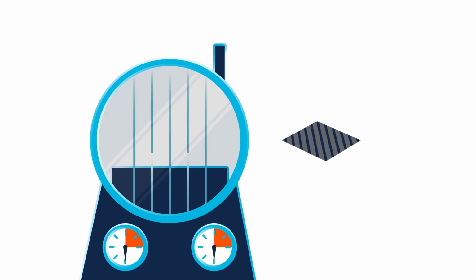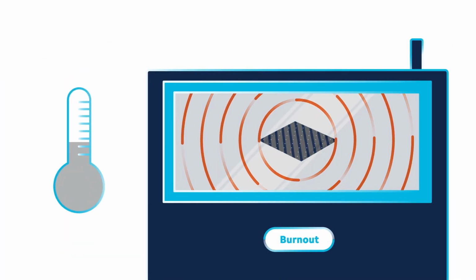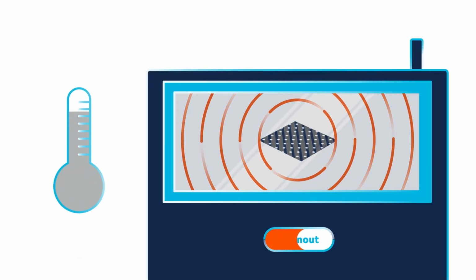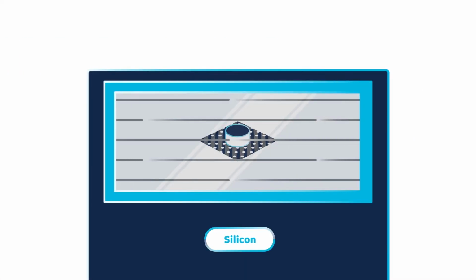The part then goes through a burnout process to convert all remaining organic material to carbon. The open pores created by the burnout process are melt-infiltrated with silicon to add density and complete the conversion to a SiC fiber and matrix part, capable of withstanding 2,400 degrees. Still, there's more to be done.